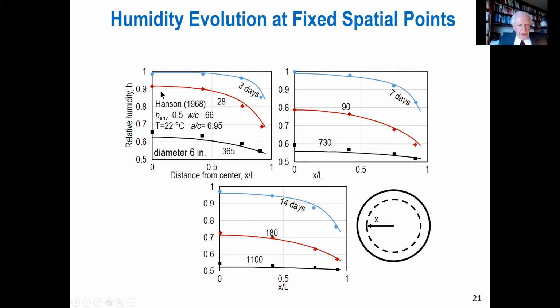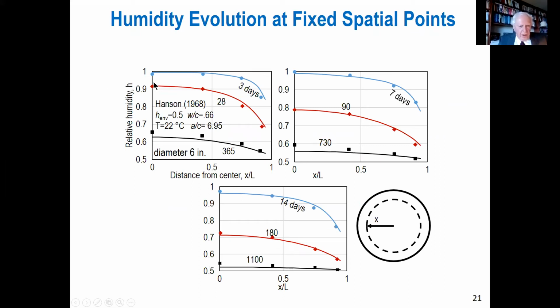Now, also what can be measured is the profile of humidity in the specimen. This is the drying surface. Sorry, on the left, you have the center line. So you have distributions of humidity, and you immediately notice they don't look like in linear diffusion. It has a flat part, and then it goes quickly down. That's a consequence of the nonlinearity of diffusivity, and from that, already in 1972, Bažant deduced that diffusivity decreases almost more than 1 order of magnitude, actually almost 2 orders of magnitude. These are data from the 1960s from Skokie near us, by Hanson, using Copeland gauge for a 6-inch specimen for various days. And these are data. This is the diffusion parameter, actually. That's how it's calculated, axisymmetric for various times.